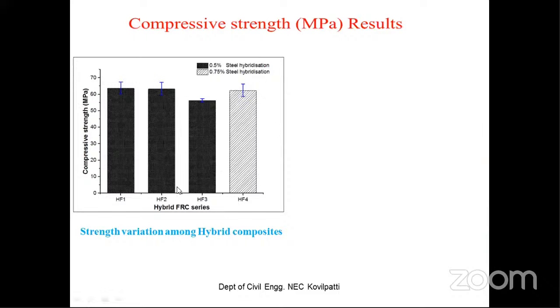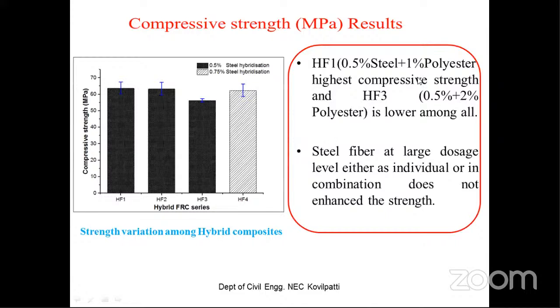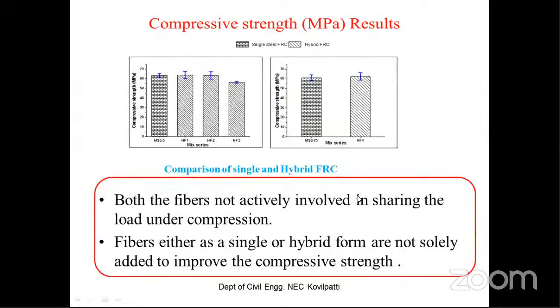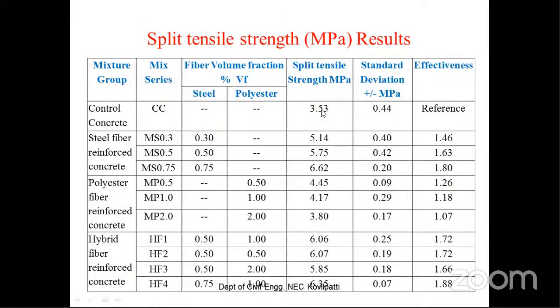And this diagram is a comparison made based on the hybrid FRC series. You can see that among the 4 series, HF3, which has the high polyester fiber, has the lowest among all the 4 series. So the conclusion is that steel fiber, either as a single dosage or in a hybrid combination, is not going to greatly enhance the compressive strength. This is the conclusion we can make. In split tensile strength, you can see the drastic change. The improvement is observed to be 46%, 63%, 80%.